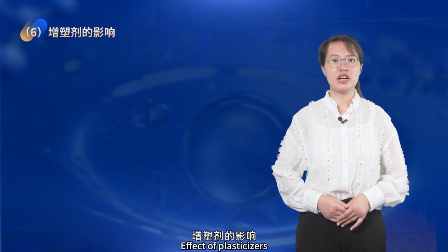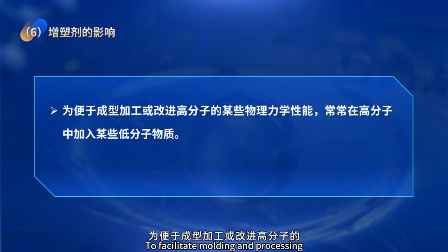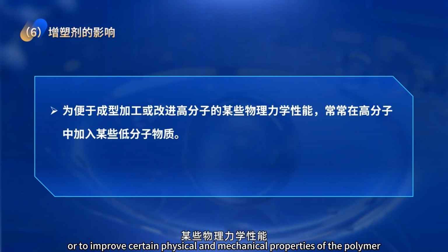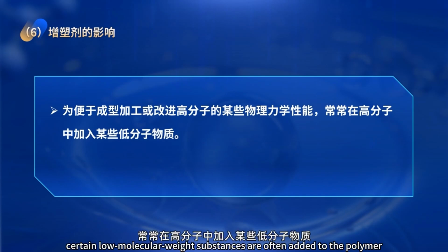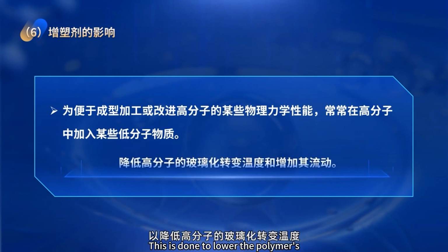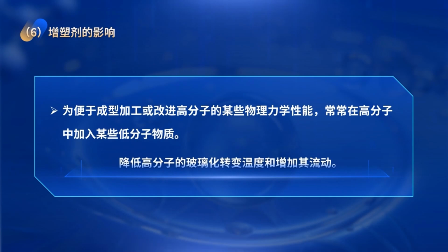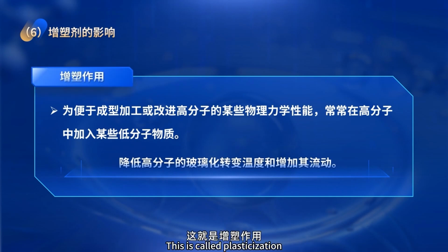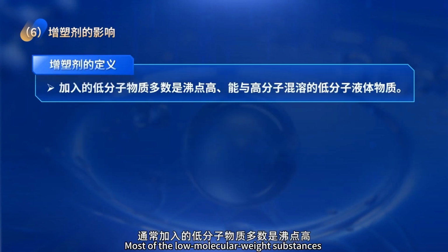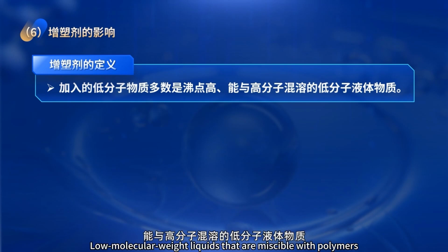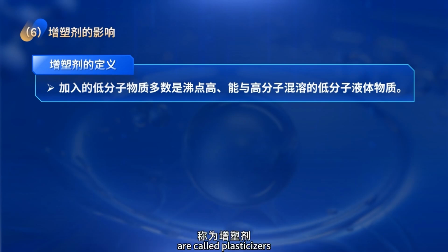Effect of plasticizers. To facilitate molding and processing, or to improve certain physical and mechanical properties of the polymer, certain low molecular weight substances are often added to the polymer. This is done to lower the polymer's glass transition temperature and increase its flow. This is called plasticization. Most of the low molecular weight substances commonly added have high boiling points. Low molecular weight liquids that are miscible with polymers are called plasticizers.